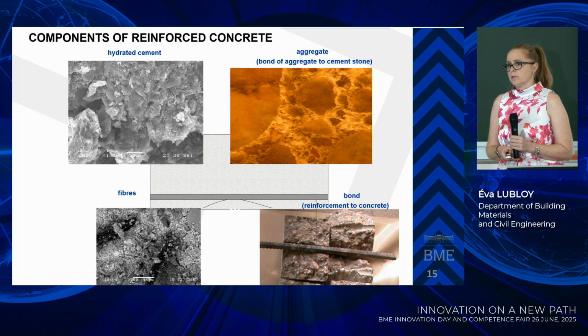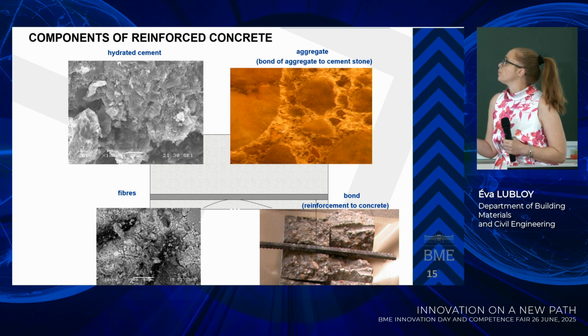Why could we have fibers? We have another problem in fire, the spalling of the concrete cover. The spalling of concrete cover comes from the escape of water in fire. Water boils in fire and will escape in the form of gas. But if we do not have pores, we have higher density, higher concrete strength, then we have spalling of the concrete cover. If you use plastic fibers, then after the melting of the plastic you have some extra holes and water can escape from the concrete.